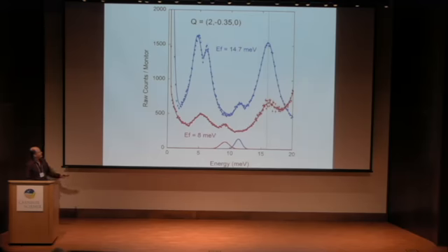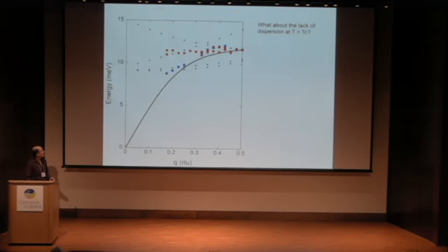If you think, well, what's going on here? This is just where the detector gets close to the incident beam. If I show you the FIT, where my optic intensity is, this is the FIT, you see that line there matches beautifully with the line here at 14.7. So there's no shift in the energy of my optic mode, which there shouldn't be by changing wavelength if it's an intrinsic mode. Okay. So Mike has raised some very, very compelling challenges to this picture, and he's right. There is no dispersion at high temperature, and this longitudinal mode certainly is dispersive.